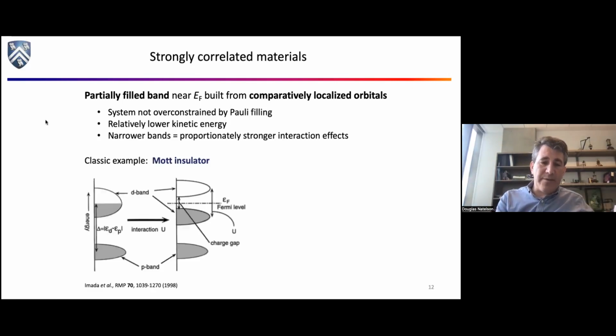And so one famous example is something called a Mott insulator. The copper oxides are based on Mott insulators, grossly speaking. If you do simple electron counting, they should be metal. The highest occupied states should be somewhere in the middle of a band that's built out of the copper d orbitals. But in practice, there's a band gap that opens up because the electrons repel each other. If you want to stick 2 electrons in the same copper d orbital, they repel each other enough that it becomes very energetically expensive. And so they kind of lock into place and can't really move very well.